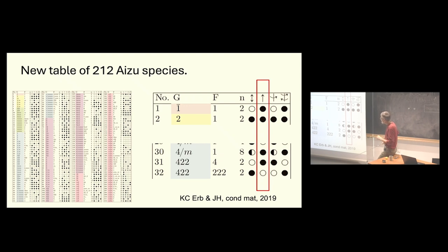So this gives you a number of the macroscopically distinguishable domains, and this is why we use these terms of macroscopic symmetry breaking also. And if you have polarization, a polar vector, and you can distinguish them, these are ferroelectric phase transitions.